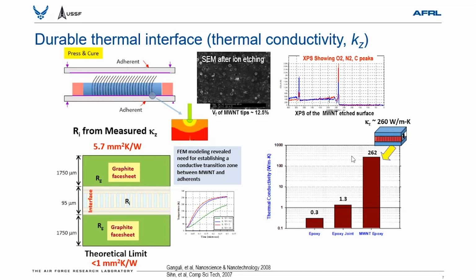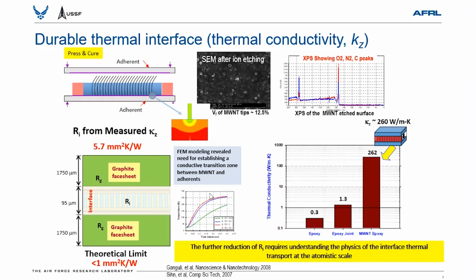So we wanted to look at this problem a little further. From these measured properties, we back calculated the interface resistance between carbon nanotube and this conducting sheet. And the interface resistance comes out to about 6 in this unit. Whereas if you do the right engineering, you can go to less than 1. So still there's room for improvement even if we showed good success in this design. That brings up the point of looking at this problem more atomistically, hence bottom-up design. So that's the nutshell, the message I'm conveying here.